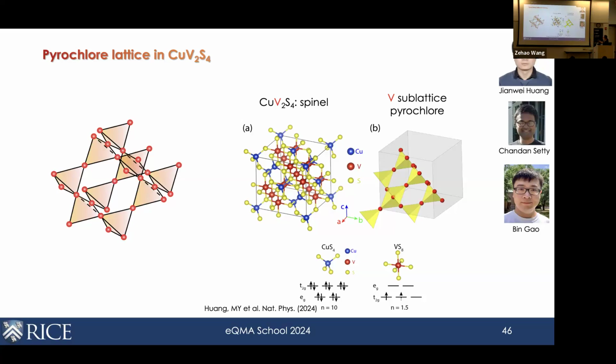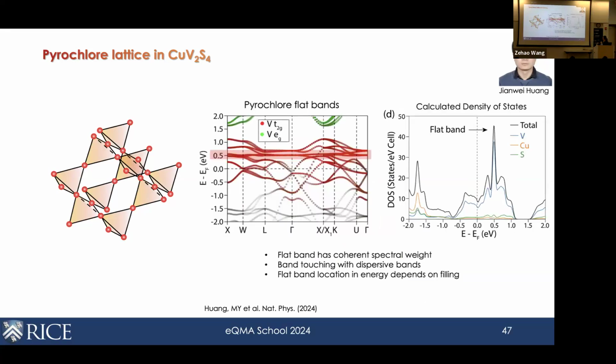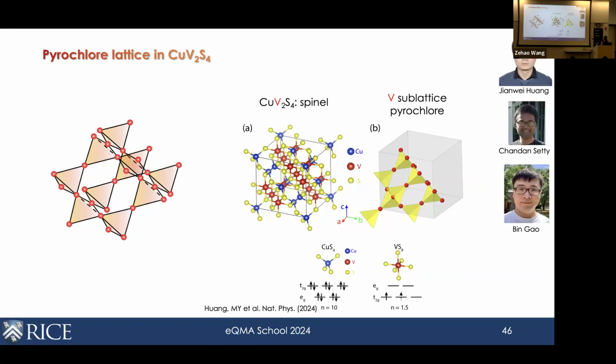So we want to look for systems where we hope to have the features preserved, right? For this, again, Chen found for us in the literature the spinel compound, copper vanadium-2 sulfur-4. In this material, the vanadium is the one that exhibits this pyrochlore lattice. What's interesting is that if you look at the structure here, the copper is surrounded by 4 sulfur, and this is basically a fully filled structure. But the vanadium is surrounded by 6 sulfur, and this is the partially filled state. So it gives us hope that perhaps the vanadium states are what's at the Fermi level, and therefore relevant to low-energy physics.